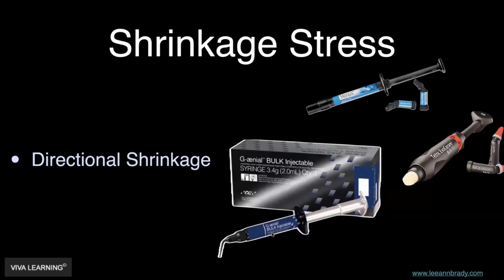So this goes to the conversation I started earlier between polymerization shrinkage and this sort of new term, shrinkage stress. Originally, when we thought about how composite shrunk, you would know that if you put a bolus of composite into a cavity preparation and then you light cure it, as it polymerizes, it shrinks to the center of the bolus of that composite. So if you think about a class 1 cavity preparation and you put composite in it, the center of the bolus of composite is in the center of the cavity preparation, away from all the walls. And as it polymerizes, it's shrinking toward its own middle, and it's pulling away from the margins.